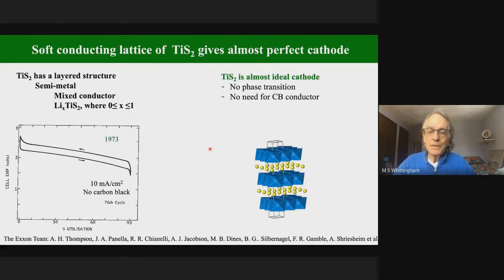So let's briefly look at lithium titanium disulfide. Why was it special? It is essentially, for all practical purposes, a metallic conductor. So electrons can move in and out very fast. This means when the lithium ions move, they're shielded from the electrostatic interactions with the host lattice, so they can move very fast. The other advantage of this particular compound is that it is what we call a solid solution. So the structure doesn't change at all from 0 lithium to 1 lithium.